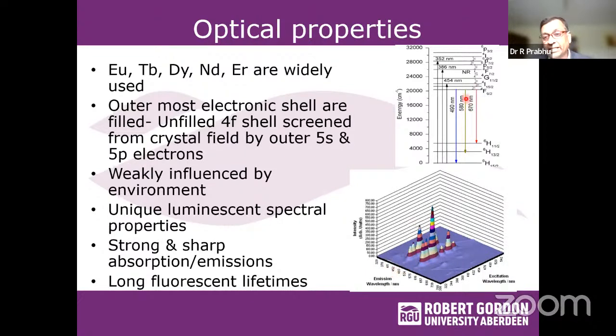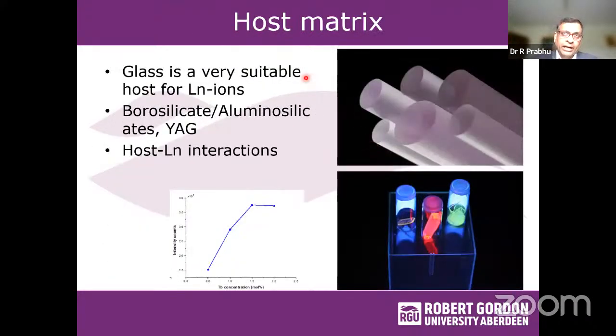In addition to that, the excited state lifetimes of these ions are quite long, varying from a few microseconds to milliseconds. That provides an additional advantage for rare earth elements for optical applications. One of the popular host materials for these lanthanide ions is borosilicate glass or aluminosilicate glass. Yttrium aluminum garnet, which is well known, has been used as a host material for neodymium, and this has been used for developing Nd:YAG-based solid-state lasers.